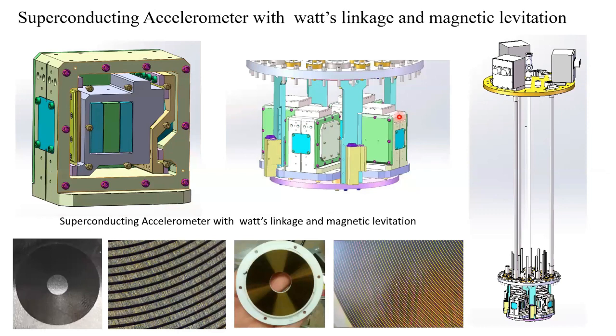Okay, so actually we have already started to try out our ideas. This is our new gravity gradiometer. It's a mixture of Watt's linkage and superconducting magnetic levitation, and the frequency is tunable with magnetic levitation. In our detector, the inverse pendulum effect is dominant. So at room temperature, this test mass is not free. It just sits on one side of the sensing coils. When it's cooled and becomes superconducting, we can store current to push the test mass, to center the test mass and make it free.